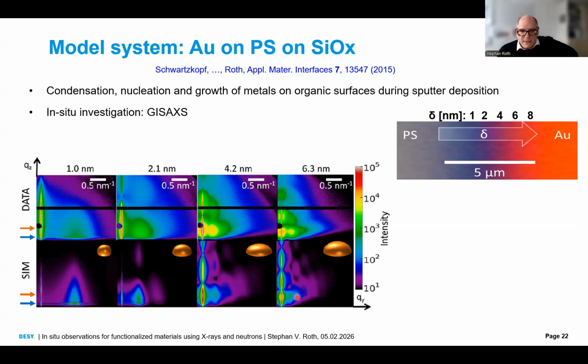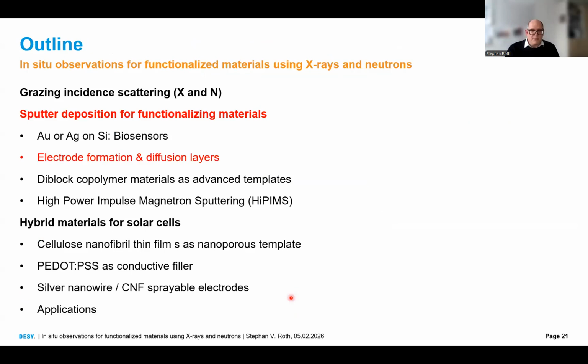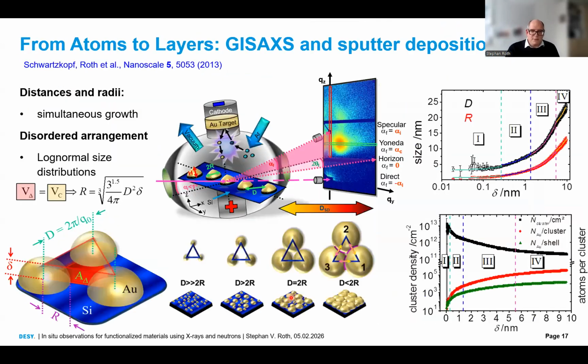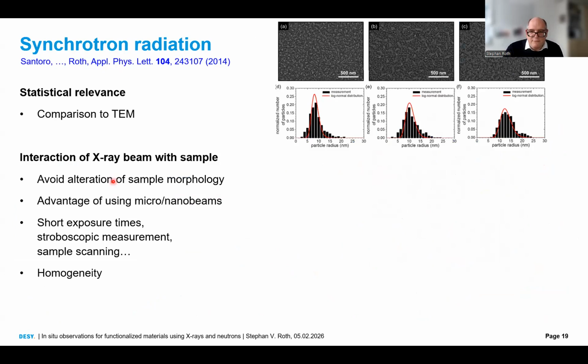And then you see the side peak here, and the side peak gives you the distance. So I know the distance of my particles, and then via this formula here, which I gave, which is a purely geometric formula, we just assume that the deposited amount is distributed into these clusters, you can deduce the radius under the assumption that they are hemispheres. If they are spheres or cylinders, this factor here changes. But this is then one of our key features.